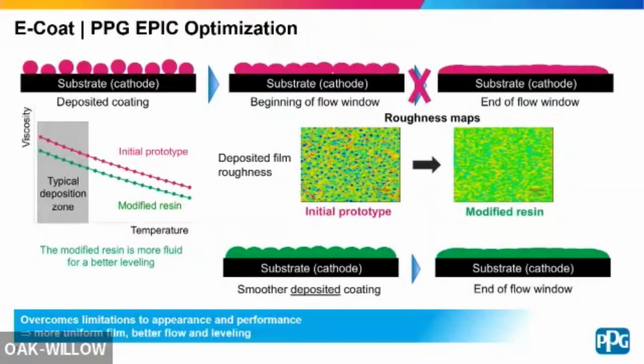So from the beginning, we have to re-engineer a resin. So in typical Ecoat formulation, you basically have a droplet. It hits the panel, it flows, it goes to the bake oven, and you start the cross-linking process. You cannot start the cross-linking process before you've optimized your flow, because if you do, you don't have edge or pinhole coverage, and there's a slew of other things you just won't get. So you're on a seesaw, right? If you're a formulator, we both started in the lab, you have to get off the seesaw. So how do we do that?